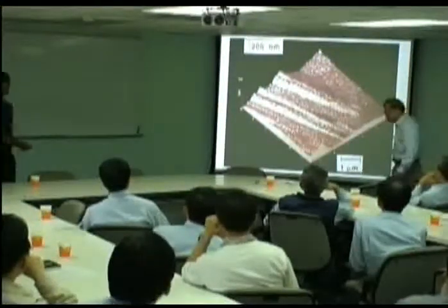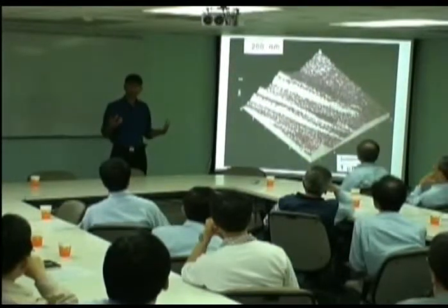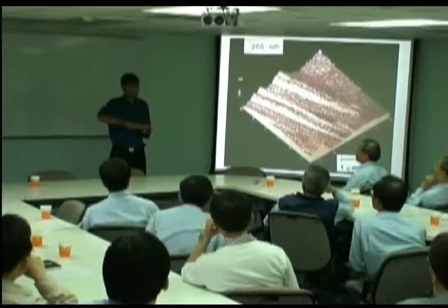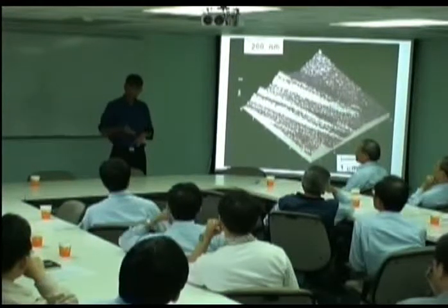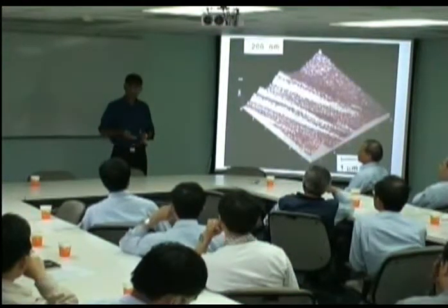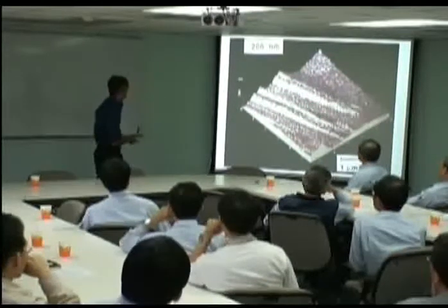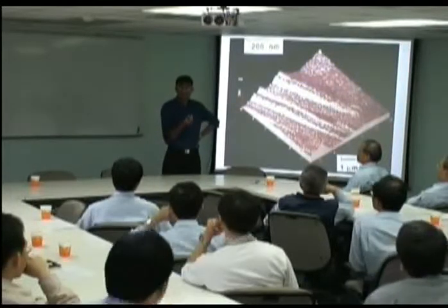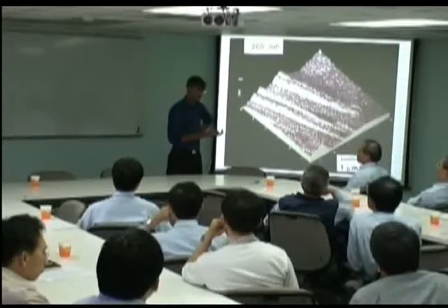Of course, this shape deformation, the shear strain and so on, is not imaginary. It really happens. If I take a specimen of austenite and polish it completely flat, mirror finish, then I allow it to transform to bainite, then I will see the shear deformation. Now, bainite is usually extremely fine. It's less than a quarter of a micrometer in thickness. Martensite can be much coarser.